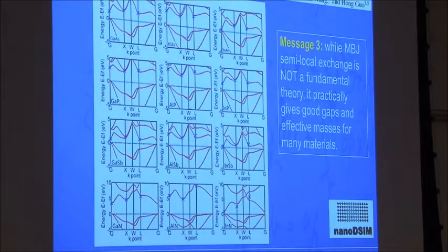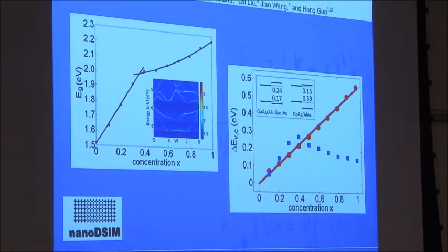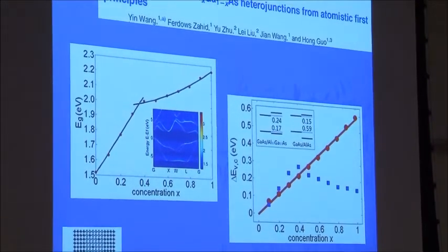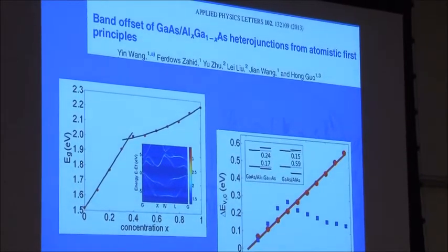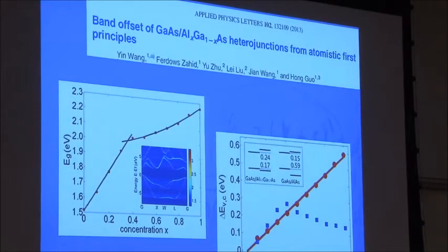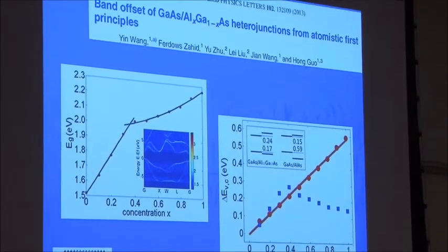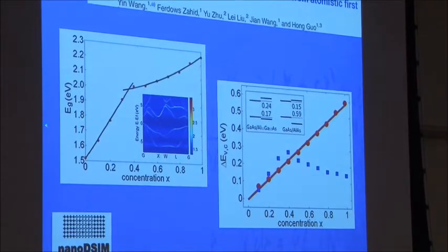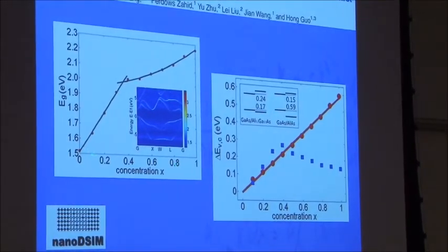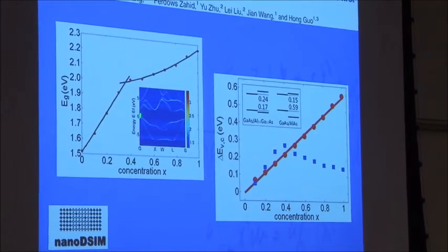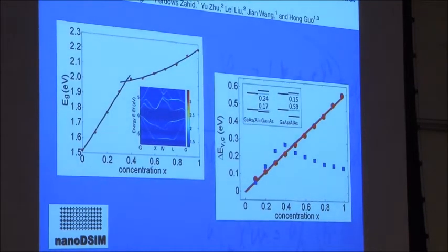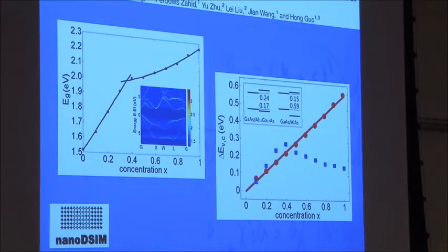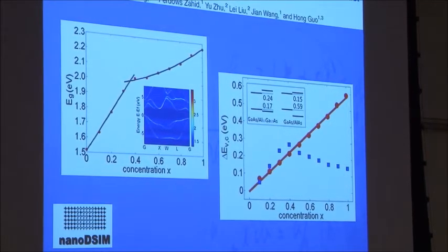This works not only that, we can calculate the band alignment between gallium arsenide and aluminum gallium arsenide. And I told you that we learned how to dope this. So we can calculate the band alignment as a function of doping concentration. This is something that I wanted to know when I was even a postdoc, a long time ago. It was never solved. So you see the band gap of aluminum gallium arsenide as a function of x changes from direct band gap to indirect band gap at 38%. And all of this agreed perfectly with experimental measurements. So this is the first time that we can calculate the entire band alignment. So for semiconductors, this works nicely. We are testing on Schottky barrier, metal-semiconductor interfaces. That is harder to do, but at least this is progress from the band gap point of view.